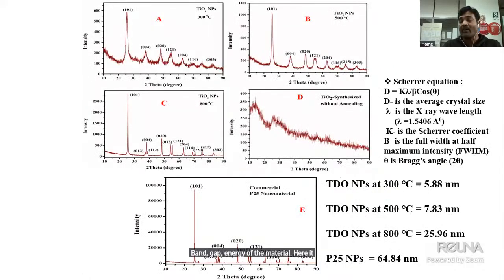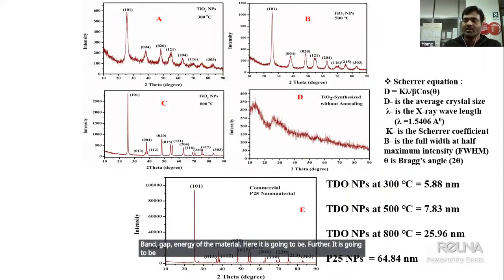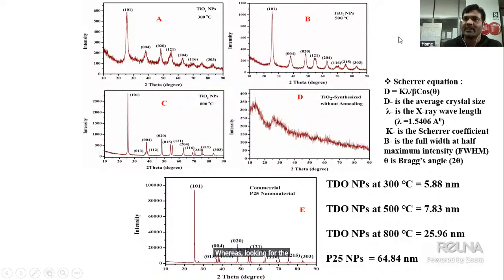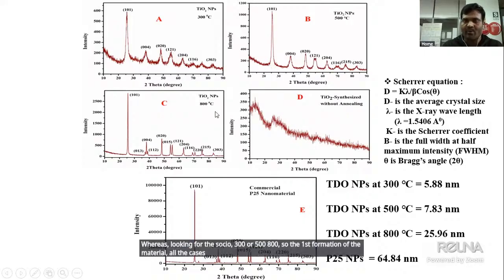Further it is going to be confirmed by the XRD analysis. XRD analysis confirms the crystalline nature of the material. We can see here that without calcination, there is no phase formation of the material. Whereas looking at 300, 500, 800, they show the phase formation of the material. In all cases it is confirmed by the XRD analysis, confirming the structure of the material.